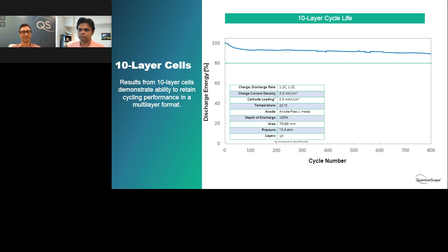So this pressure that was applied to our 10-layer cell is just the same as for a 1-layer cell, indicating you don't need to increase pressure as you increase the layer count. Really, pressure is going through all the layers in the normal direction. So pressure you apply to the first layer is applied to all the layers below that. I think there's been some misconceptions about that. So these are some of the points to note about this result. Venkat, anything further that you wanted to note?